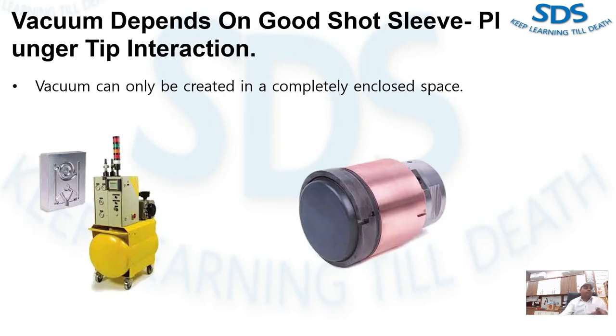Okay, so vacuum: it is the obvious fact that a vacuum can only be created in a completely enclosed space. This makes the seal between the plunger tip and the shot sleeve critical to vacuum assisted die casting. The gap between the plunger tip and the wall of the shot sleeve is necessarily very small. If at any time during the return stroke of the plunger it becomes too great, air is likely to be sucked through the gap. Also, during the injection, the metal may penetrate the gap.